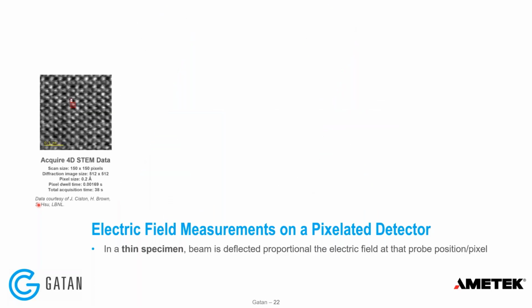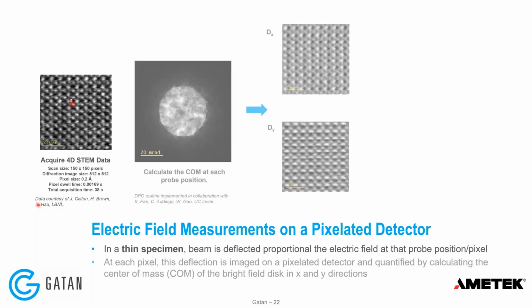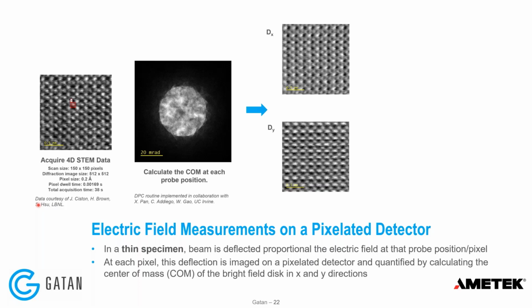So here I'm showing an example of high resolution data for the STEM data acquisition. This was actually collected at NCEM using the K3 IS at the end of an imaging filter. For DPC imaging, you want to be in large convergence angle conditions, and you are imaging the direct beam, the 000 beam. And what we do is we look at the contrast within the disk, and we measure the shift in the center of mass of the beam at each pixel position.